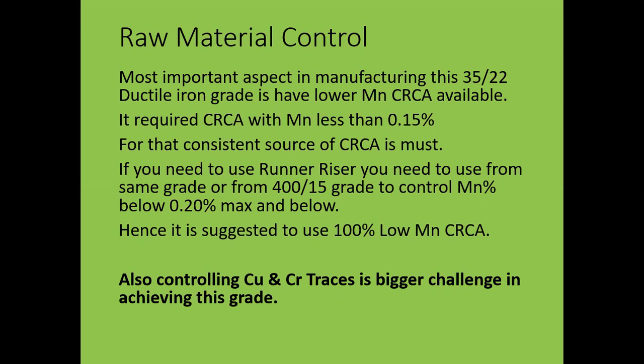Raw material control. First, we are going to see what raw material control is required in making of 35 by 22 grade of ductile iron. The most important aspect in manufacturing this 35 by 22 ductile iron grade is to have lower manganese CRCA availability. It requires CRCA with manganese less than 0.15%. For that, a consistent source of CRCA is a must.